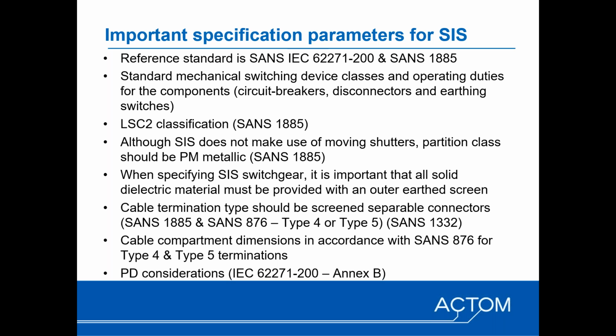So when it comes to single core cables, like for example, which are used at 33 or 30 kV, we're using 36 kV switchgear. The SANS 876 has been amended to accommodate applications where it is known that single core cables will be used, and those dimensions have been reduced.